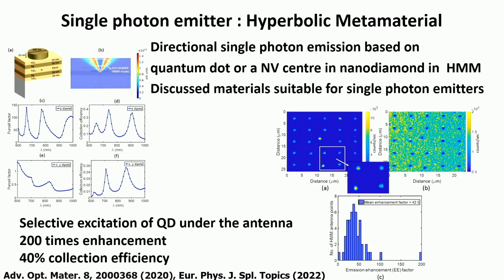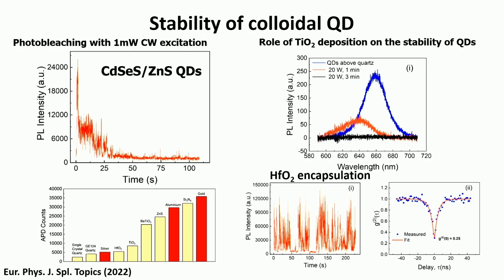Now, one of the challenges if you use a nanoparticle is that it suffers from blinking. So the excited electron goes and sits on top of the defects on the surface. And it takes a long time for the electron to decay down to the ground state and then start contributing back to the PL emission. So this is a blinking effect, and the other one is bleaching, the photo bleaching. Even with a few microwatts of average power, if you keep shining, the nanoparticle just saturates, it just dies. It stops emitting anymore.